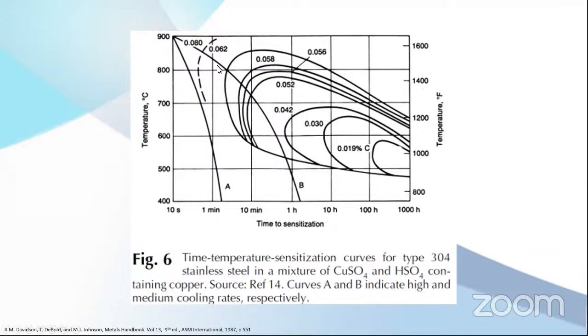But if you have slower cooling, or let's say a multi-pass welding, so it stays in this temperature region for some time, the cooling curve will reach one of these noses, and then chromium carbide starts to precipitate. So low carbon stainless steel is set at 0.03, so the cooling has enough time. It's like 1 hour to cool before it starts to sensitize. Even lower carbon, you can have longer time to sensitize. So 0.03 is the L grade, for example, 304L or 316L is this line. So I would say it's pretty safe for any welding, with cooling not reaching this line.